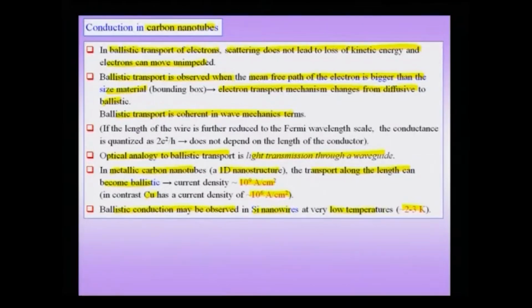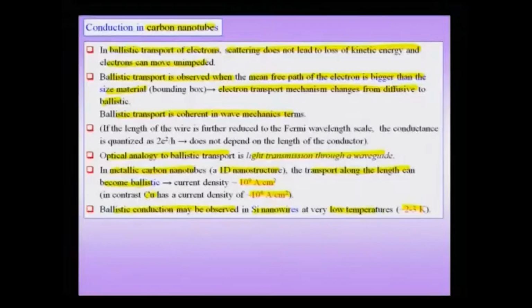So, to summarize this slide, we have noted that a system size can become so small that normal drift transport or diffusive transport switches to what you might call ballistic transport, where there is no scattering of the electron, and when this happens, you can attain very high current densities, as in the case of metallic carbon nanotubes along the length of the nanotube, and this kind of current density is much higher than what you typically obtain even in a good conductor like copper.